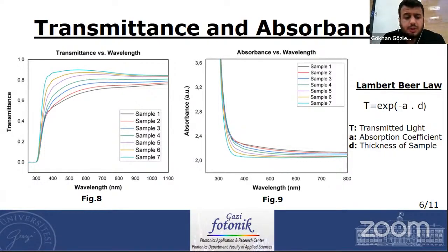Titanium dioxide thin films have low absorbance in the longer wavelengths. It's clearly seen that absorbance is relatively low in the range of 380 nanometers to 800 nanometers. However, titanium dioxide films have high absorption in the UV wavelength region of 250 nanometers to 380 nanometers.